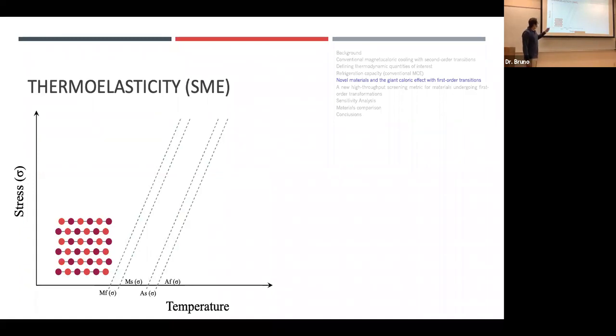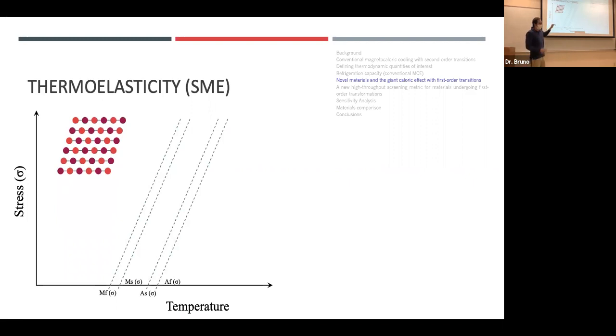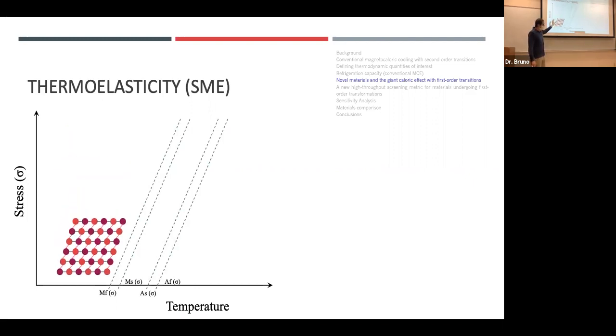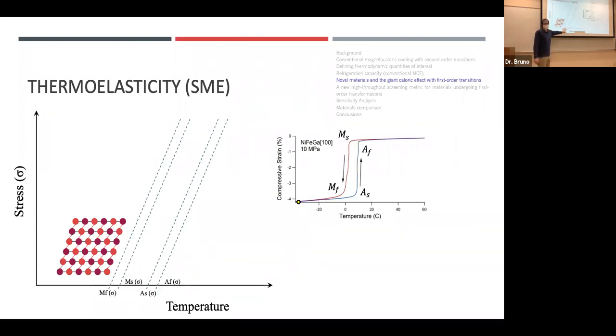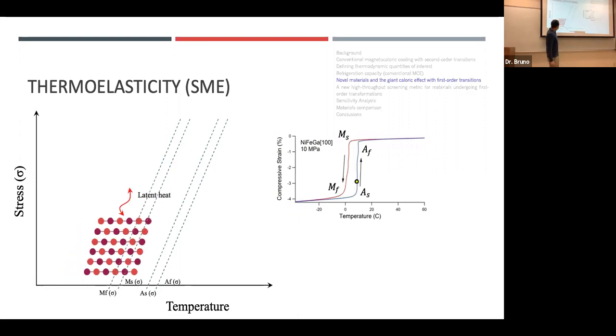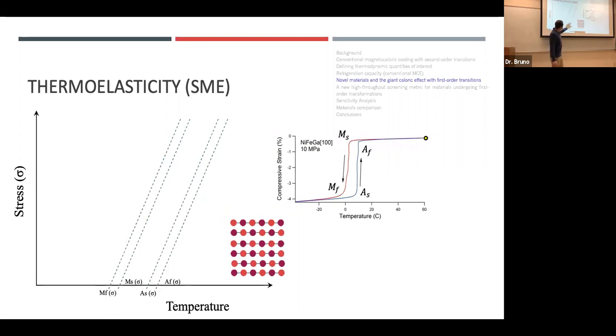So these materials exhibit something called thermoelasticity, or the shape memory effect, where at low temperatures we have some, say, twinned martensite. This is a stress versus temperature diagram. If we apply a load, we will actually detwin the martensite, and we get some large deformation. When we unload the detwinned martensite, we can actually recover the shape of the original material by then heating it up across some critical transformation temperatures. If we heat it up, we're going to thermally expand martensites until we get to some austenite start temperature. And when we heat it up beyond austenite start, we actually get a phase transformation from martensite to austenite, where we are no longer non-cubic, we have a different crystal structure. Then if we cool it off, we're going to transform it back to martensite and be in our original shape.